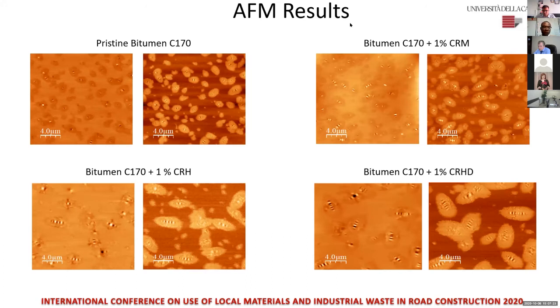So here we have these domains of the asphaltenes, which are less than 4 micrometers in size. You see the domains here, they are small. These are the asphaltenes of the pure pristine bitumen. Now, when we added the bioadditive, you can see that these domains increased slightly in size.